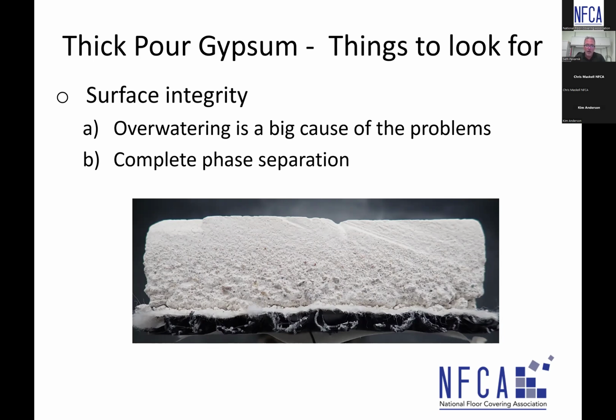Now, you remove that weak surface, you get down to the sand and the cement, you'll get to a hard surface. But, looking at this picture, if it was hypothetically 3/4 of an inch thick, then we need to remove 1/4 of an inch to start to get down to the hard stuff.